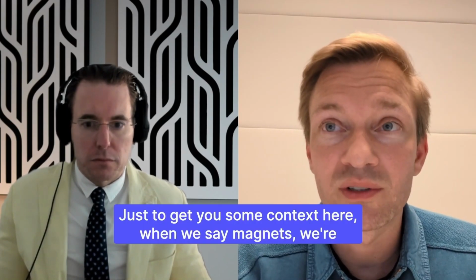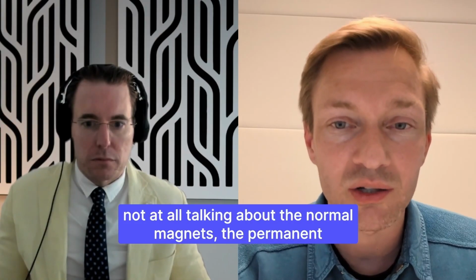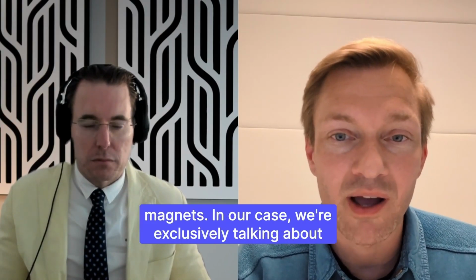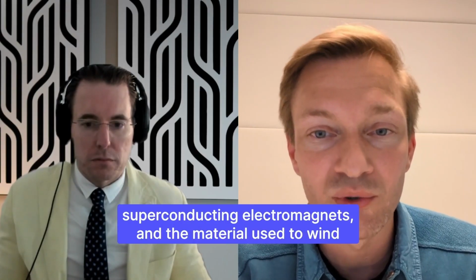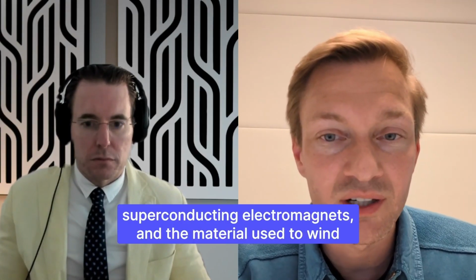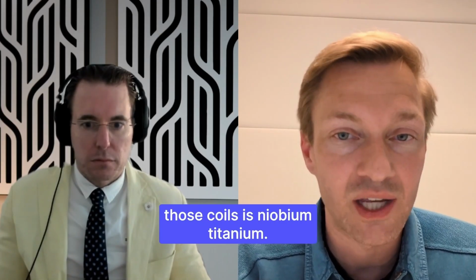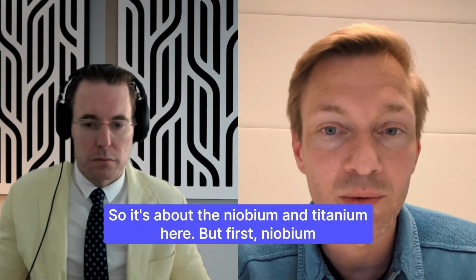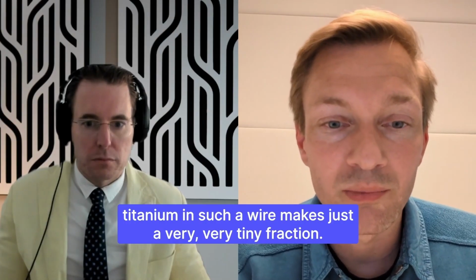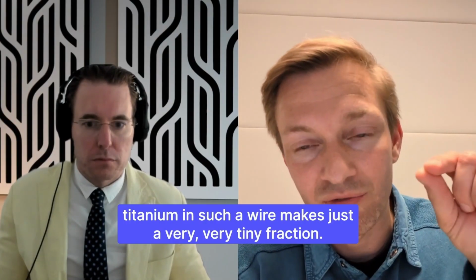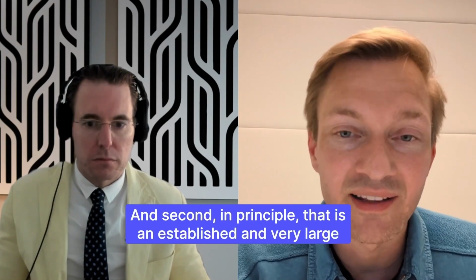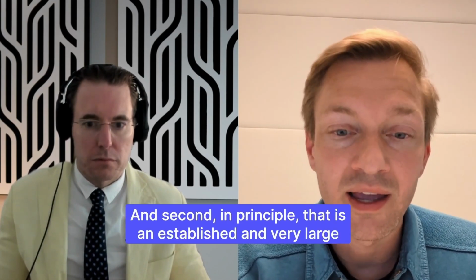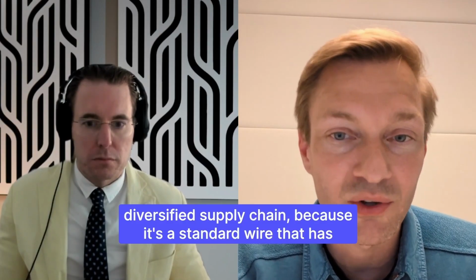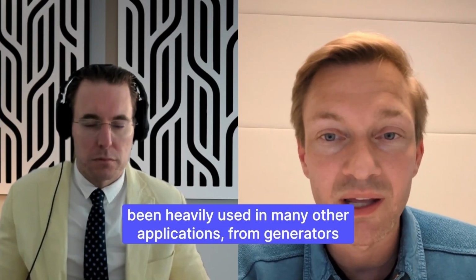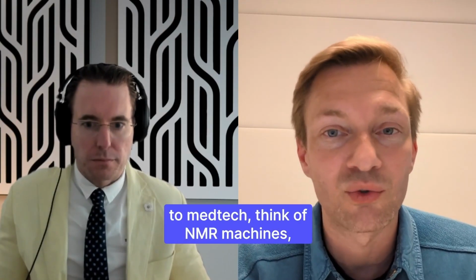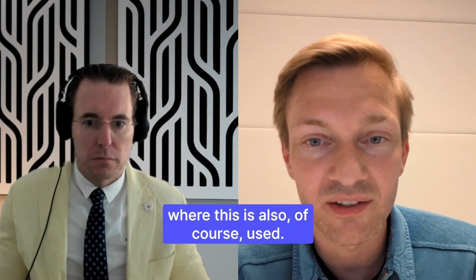Just to give you some context here, when we say magnets, we're not at all talking about the normal permanent magnets. In our case, we're exclusively talking about superconducting electromagnets, and the material used to wind those coils is niobium titanium. But first, niobium titanium in such a wire makes just a very, very tiny fraction. The greatest part of the wire is copper. And second, in principle, that is an established and very large diversified supply chain, because it's a standard wire that has been heavily used in many other applications, from generators to medtech. Think of NMR machines, where this is also, of course, used.